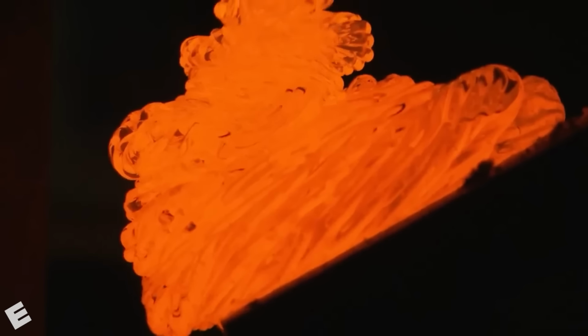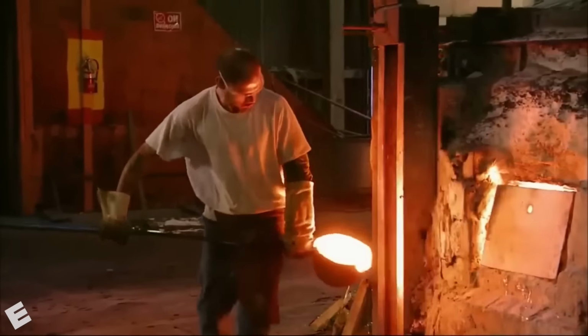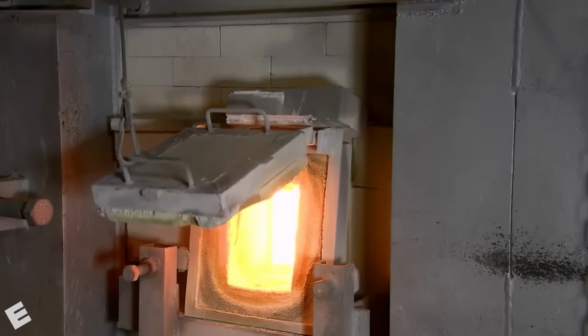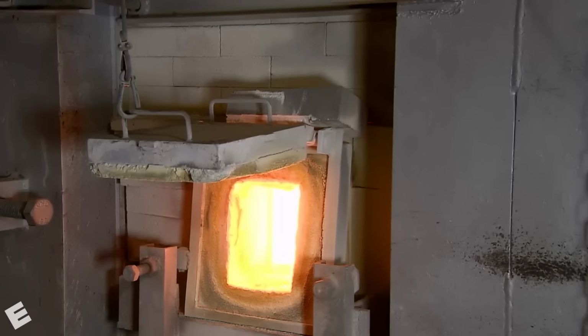At the bottom of the furnace, what shines so brightly is now liquid glass, a thick, glowing mass that has reached the perfect temperature and consistency. Over the next several hours, the glass remains molten, allowing any remaining trapped gases to escape, so the material becomes as pure as possible. The furnace contains 12 separate crucibles, each capable of holding a different color of molten glass.